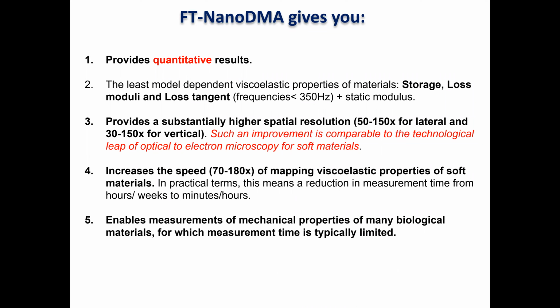So what about this mode? It gives quantitative results. What does quantitative mean? Quantitative is really absolute measurements, not relative. How can you know it? First, of course, you compare. You can compare with known materials. Second, it's important that we don't have crosstalk between different frequencies. Because if we don't have that, we work in the linear regime, the linear stress-strain regime. This linearity is important for all contact and all mechanical models. If you see crosstalk between different frequencies, then you are in the nonlinear regime, so your information cannot be trusted. So that's why you have a kind of feedback to understand if your measurements are trustworthy or not.